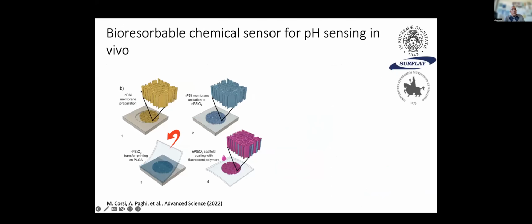So we started with the porous silicon, and then we do the oxidation, and then we transfer print the porous silicon membrane on a PLGA substrate. This is because we want to go in vivo, and we want to be bioresorbable, so we cannot implant the full silicon chip. The porous silicon membrane is just 5 micrometer thick, and the PLGA layer is also 10 or 20 micrometer thick.